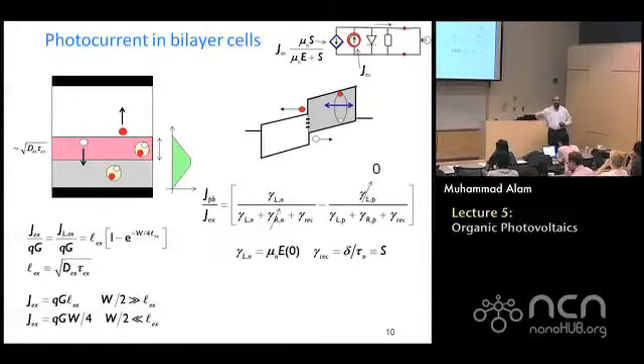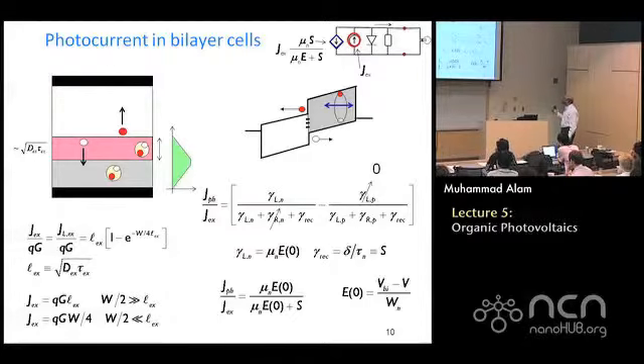If you put it in, then you get mu E naught over mu E naught plus S. S is the interface recombination, and that immediately tells you that this current cannot be voltage independent. Do you see why? This electric field E naught is the electric field here. That electric field is VBI minus V, the applied voltage, divided by Wn. This is the Wn. And as I am changing V, my E naught is changing. If my E naught is changing, this ratio is changing.